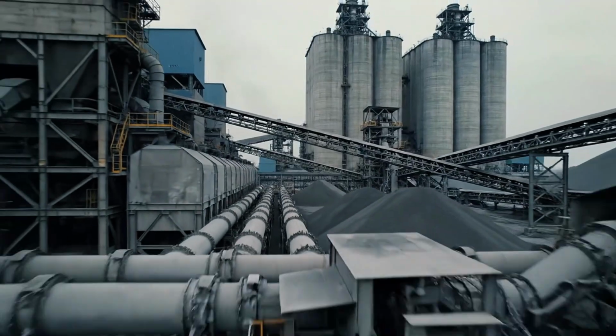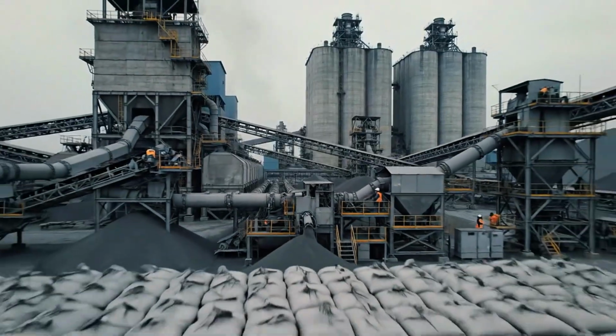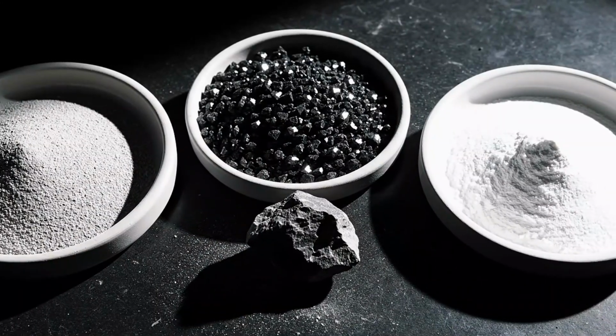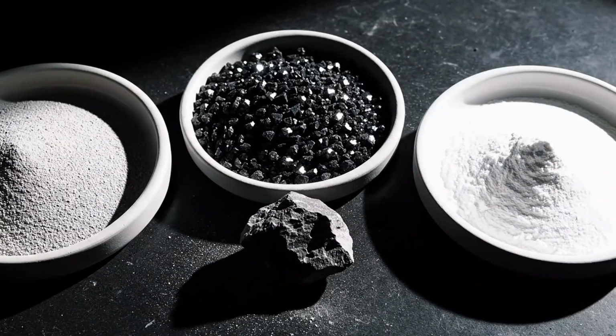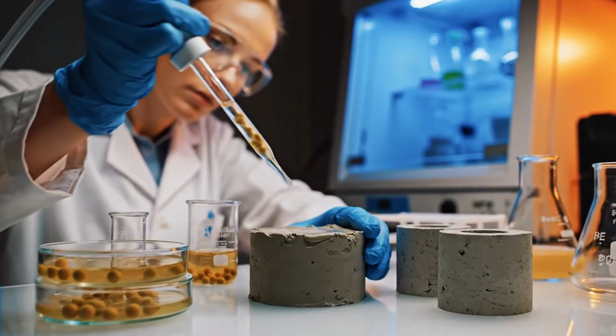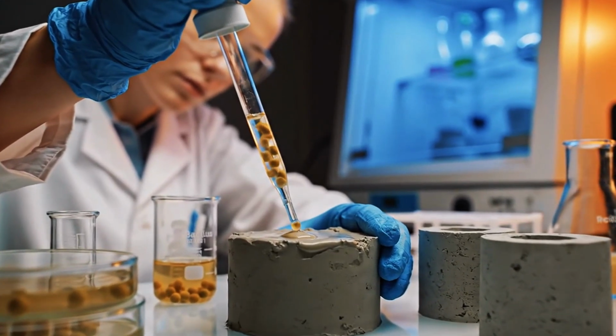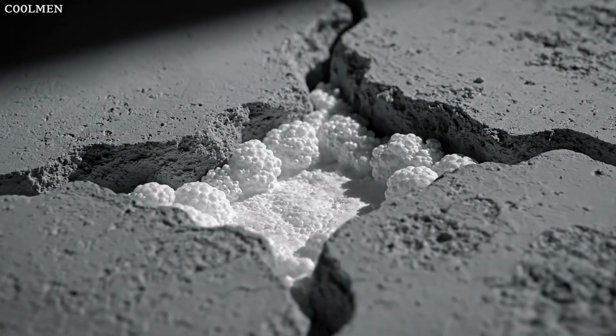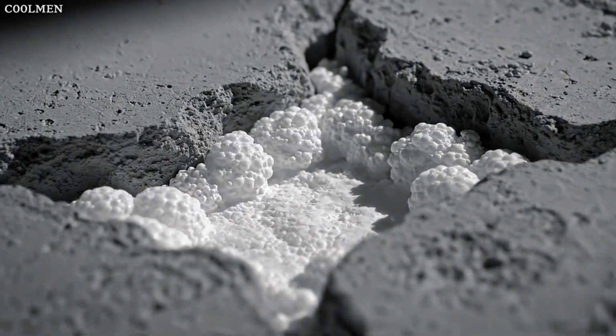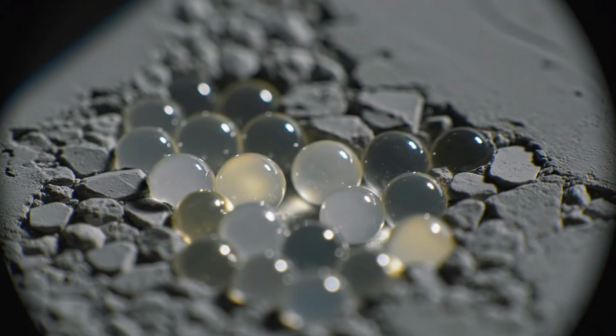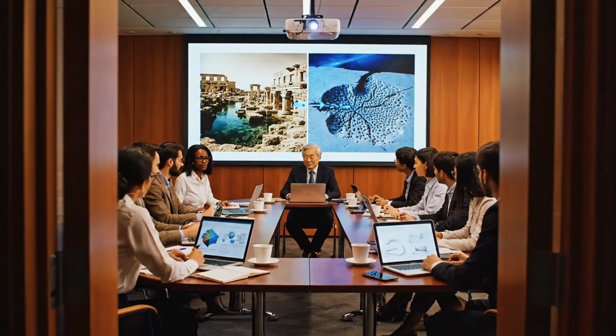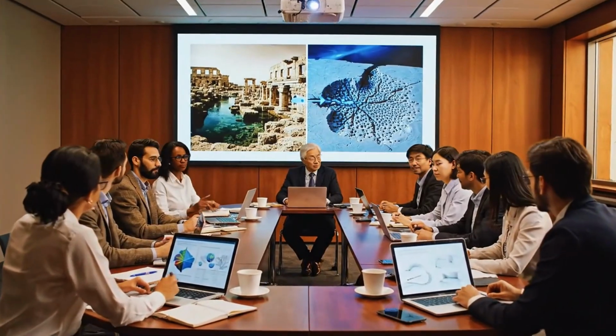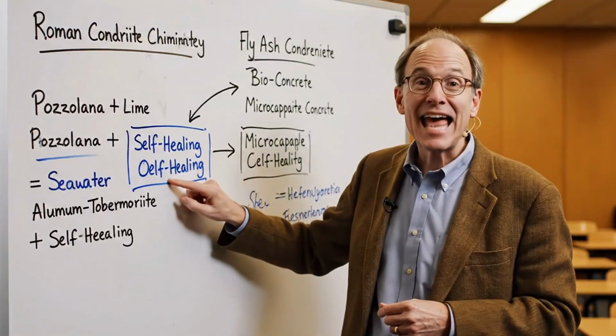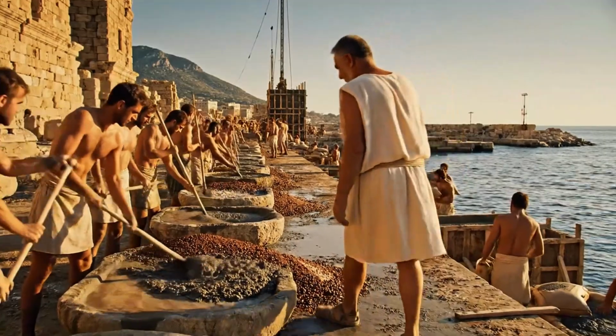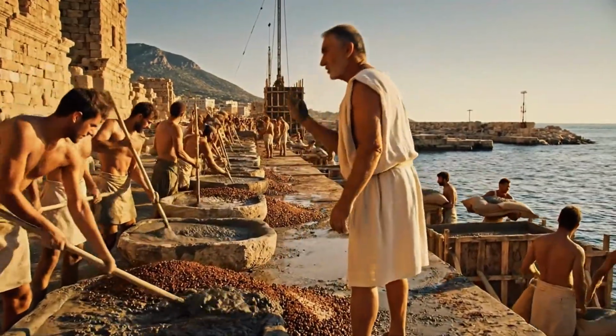There are now experimental projects using engineered volcanic ash substitutes, fly ash from coal plants, ground blast furnace slag, synthetic pozzolans, to trigger similar self-healing reactions. Some teams are developing bioconcrete, which uses bacteria embedded in the concrete matrix to produce limestone when cracks form, sealing them from within. Others are working on polymer-based self-healing systems, where microcapsules of healing agent rupture when a crack forms, filling the gap. All of these approaches are inspired, directly or indirectly, by the realization that Roman concrete wasn't just durable by accident. It was durable by design, even if the Romans didn't fully understand the chemistry.